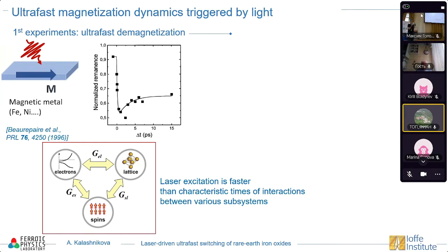Just to the end of the last century, in 1996, there was the very first successful experiment showing that ultrafast laser-driven magnetization dynamics is actually possible. The experiment was performed on nickel, which is a ferromagnetic metal. It was shown that if you take a 100 femtosecond laser pulse and excite this material, then magnetization suddenly drops by a really large degree, by 50% or so. And this drop happens on a time scale which is shorter than 1 picosecond. Then it is followed by some slower relaxation. And this experiment was the first demonstration of so-called ultrafast demagnetization.